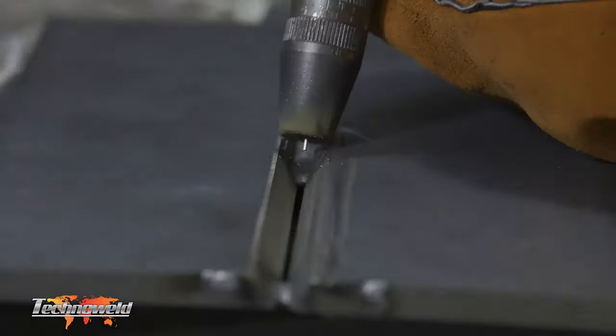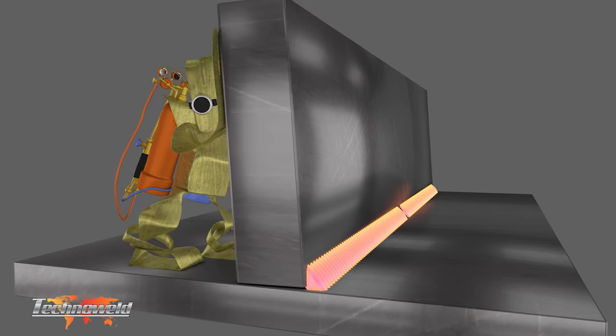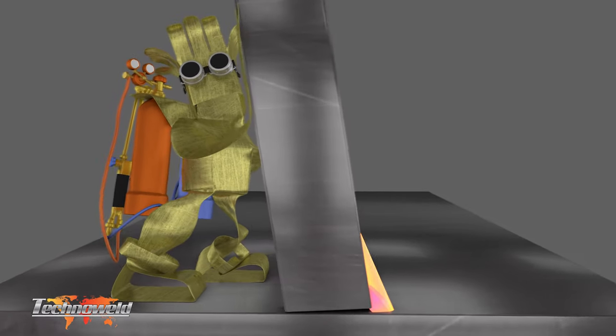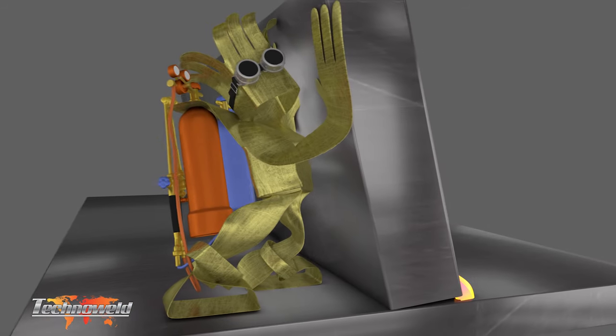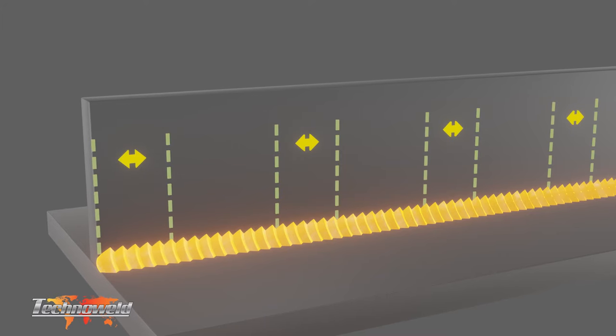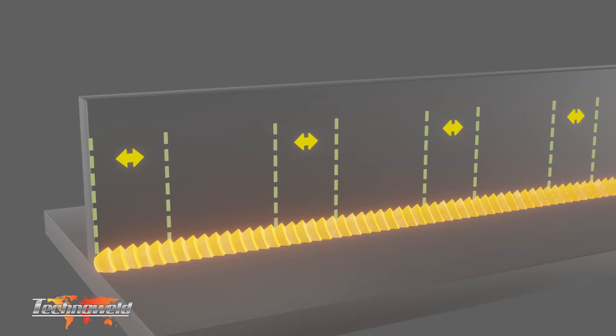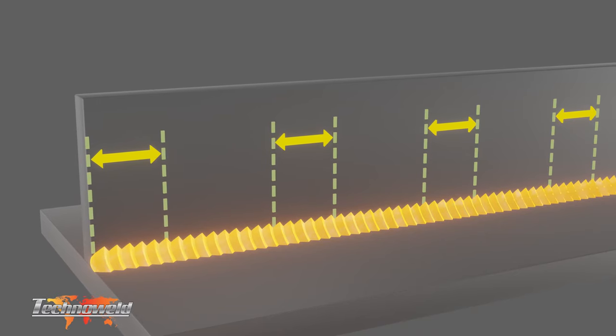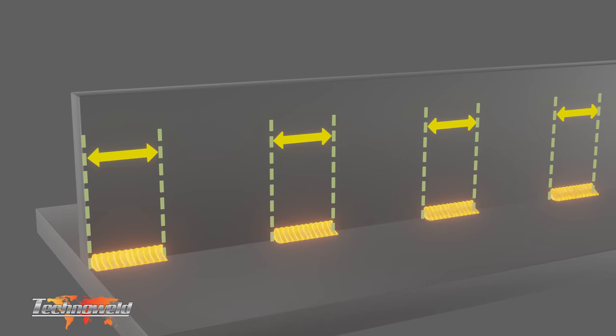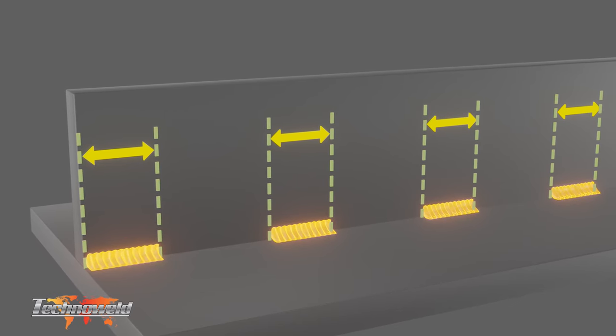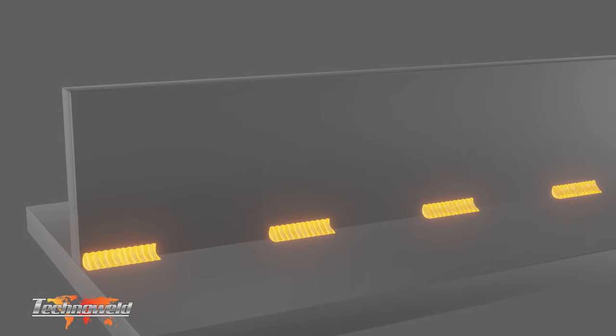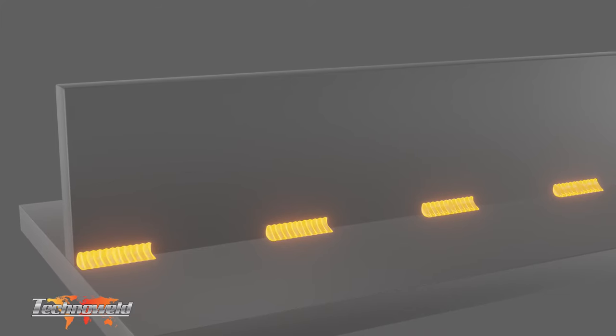Butt welds often have to be done in multiple passes: the root run, lower amps to get control, and the following runs can be turned up to allow higher deposition rates. Here we see Flexi getting to work on a continuous fillet weld. The expansion from heat causes the metal to distort. How can we reduce this distortion? Longer welds have greater weld volume. Greater weld volume increases distortion. If the design allows it, the use of stitch or intermittent welds versus continuous welds will reduce the total weld metal volume and therefore amount of distortion. In some circumstances we can use a series of short welds called stitch welds, spaced evenly along the weld joint instead of running a continuous bead. This technique is called intermittent welding, which sacrifices some overall strength but provides a reduction in distortion.